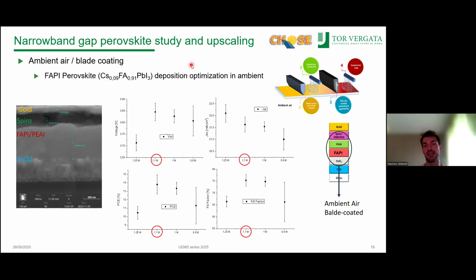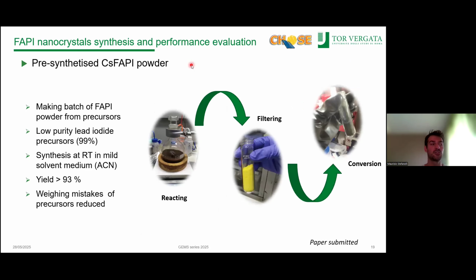We did several trials with this kind of perovskite to get a good crystallization, and several concentrations were also tested to get the right thickness of our perovskite, with an efficiency between 14 and 15% for the first trials. Then we moved this formulation to a pre-synthesized cesium FAPI powder. This means that we already react all the precursors in a mild solvent medium, in this case ACN. We also use low purity lead iodide precursor, just 99% from Sigma, and not the high purity lead iodide from TCI, for example. With this process, we can make a batch of FAPI powder from low purity precursors with a yield of 93%.